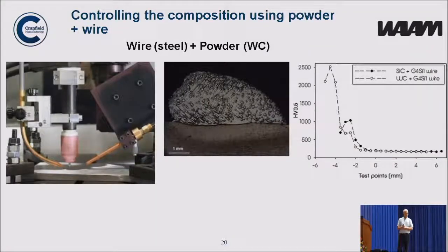In terms of controlling the properties, we can look at other combinations. In this case, we're using a wire and a powder. In the picture on the left, you can see on the left-hand side, we're feeding the wire in. On the right-hand side, we feed the powder in. And in this case, we put down a steel tungsten carbide metal matrix composite. And of course, again, you can do different combinations of these.